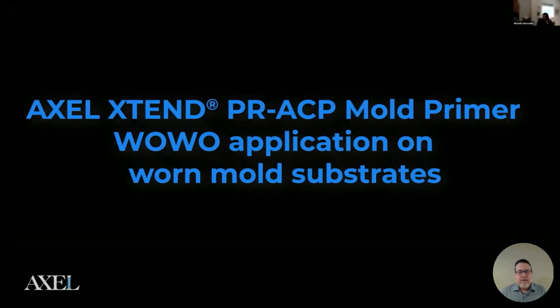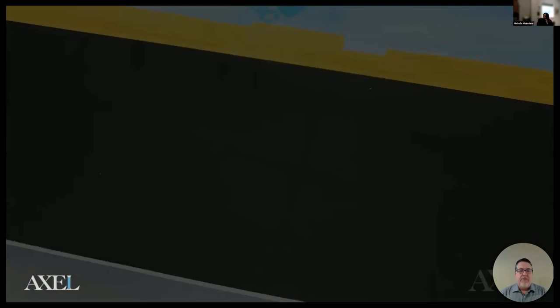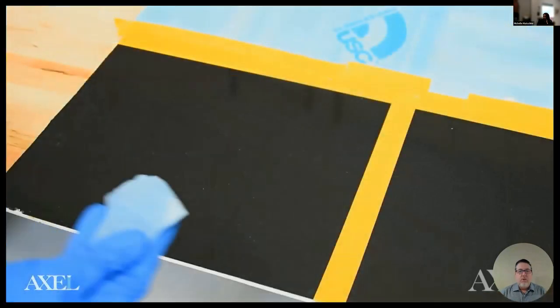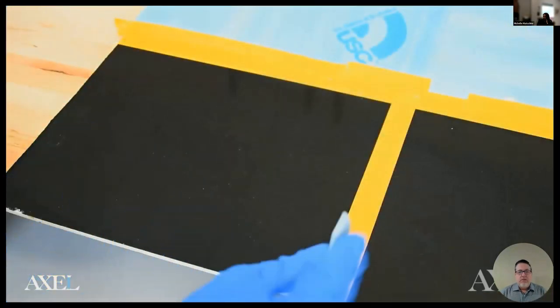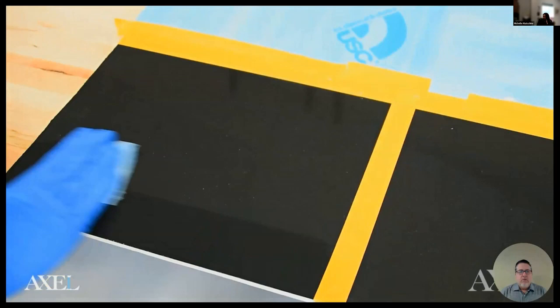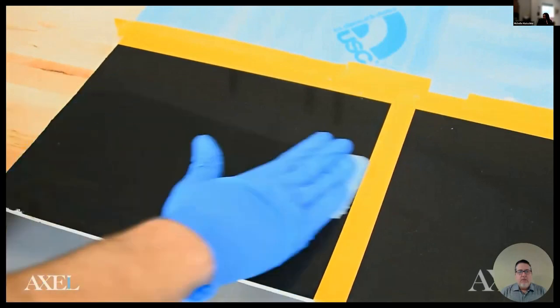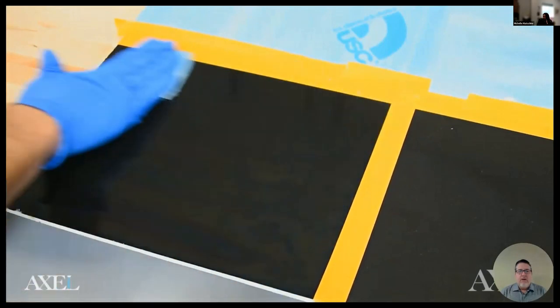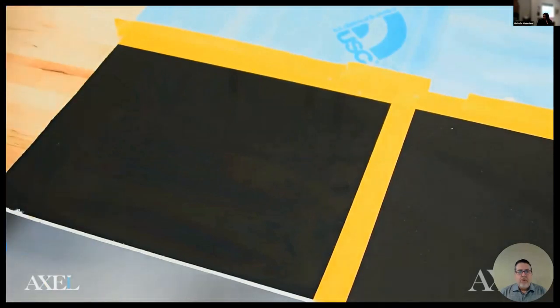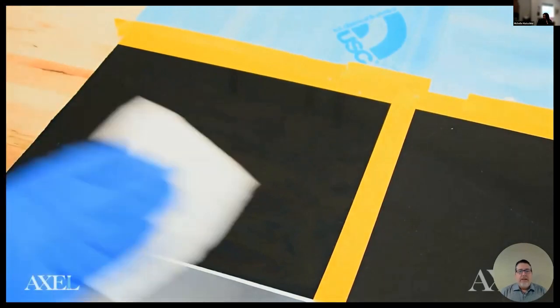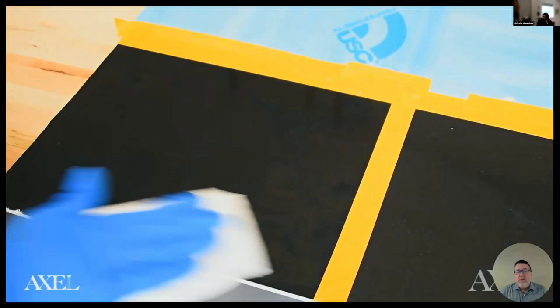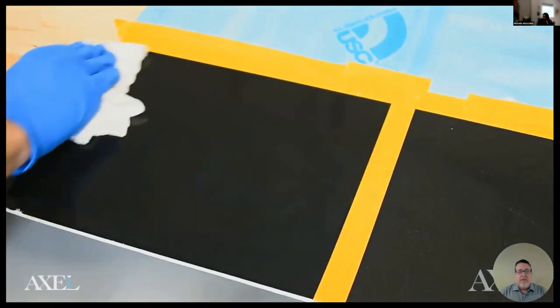So this is an application showing the primer with a wipe on, wipe off, not a buff off, but just wiping off, for what we would call a mildly worn, high gloss tooling. Here you can see our lab technician just applying a coat of the PRACP. In this case, when it's a very high gloss tool, really only one coat is probably needed. And then he's very lightly just wiping this off, as noted.